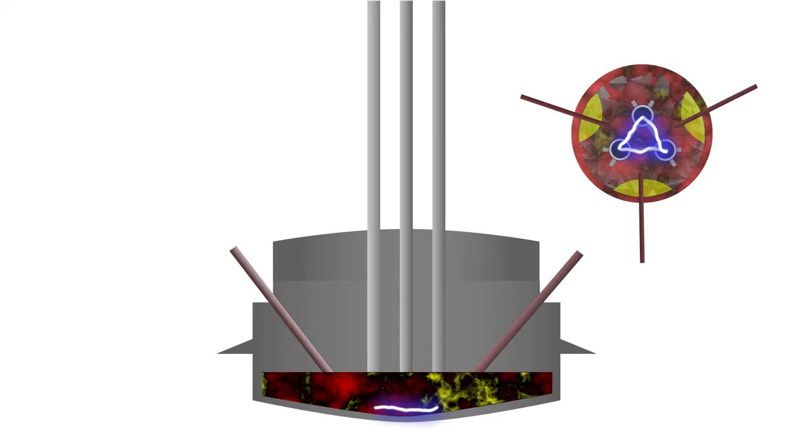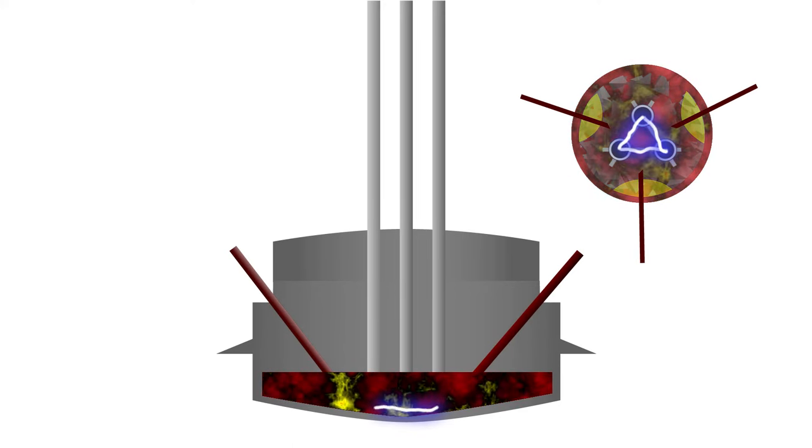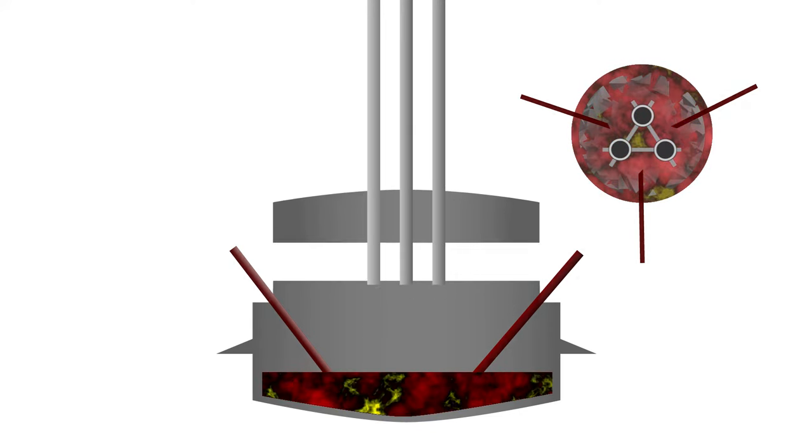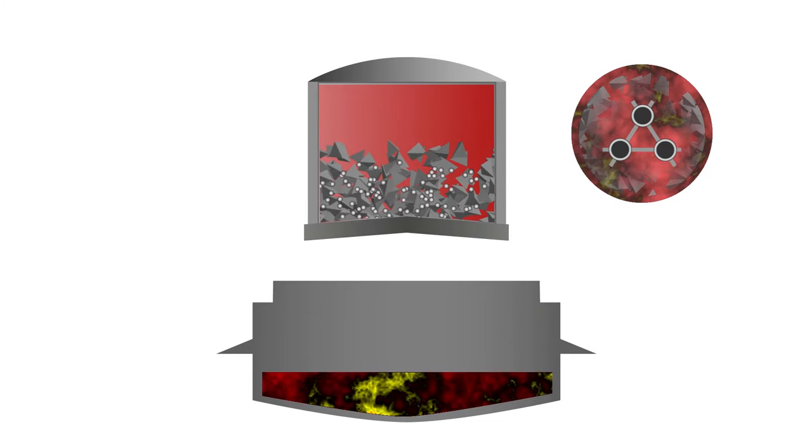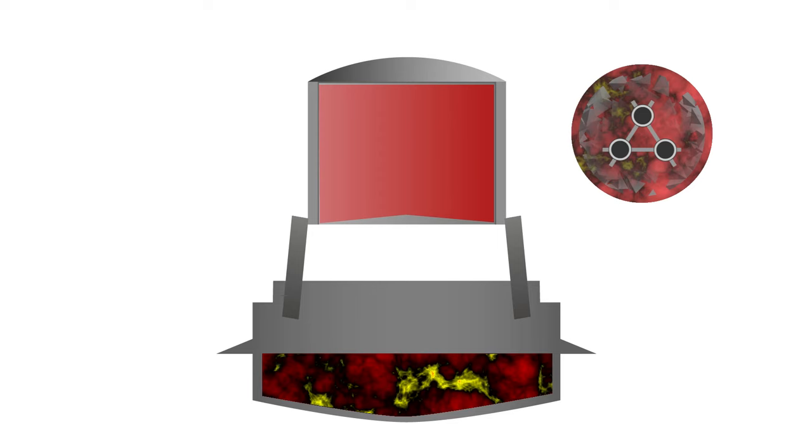Injectors that burn carbonaceous fuel, such as natural gas, located at the side wall of the furnace, provide additional heating to the cold spots to homogenize temperature. Once the charge has melted, the roof is removed and there is another charging phase, with more charge added, and the melting phase is repeated.